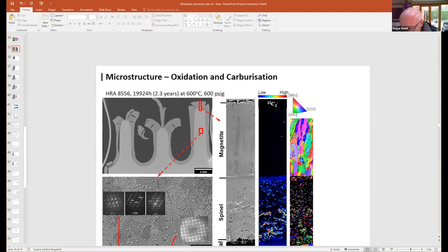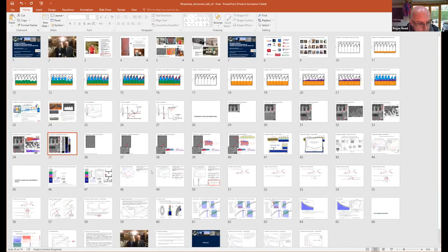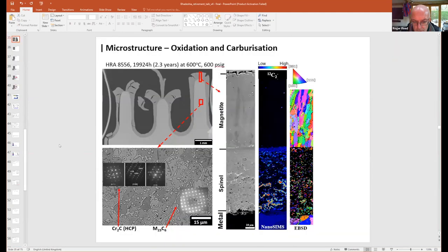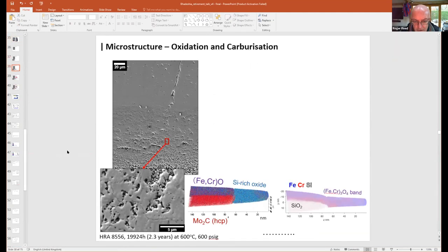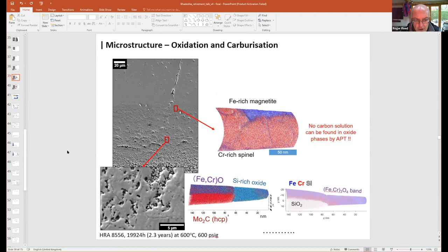And in fact, that's what I personally believe is happening here. If you look closely at these structures, the oxide is full of defects and porosity, and this is really due to the Kirkendall effect, of course, that you taught me about. You have fluxes moving in different directions, and that gives you a net flux which is not zero, and hence the formation of this porosity.